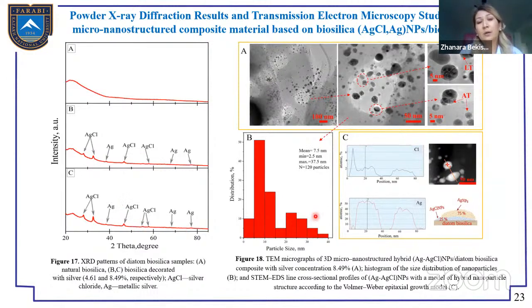And the next figure is the transmission electron microscopy study. The nanoparticles are distributed on the surface with a predominant size from 5 to 15, and with crystalline layer twin and axially twin crystalline.